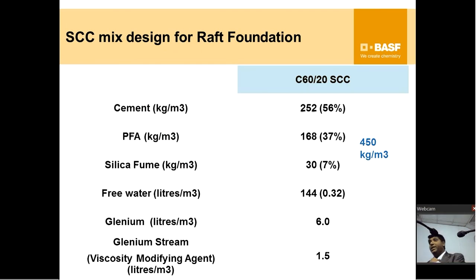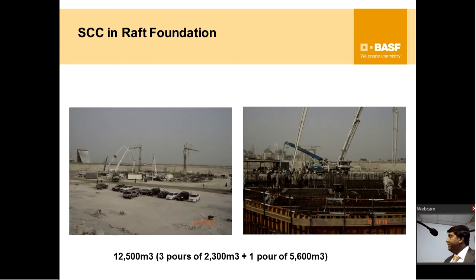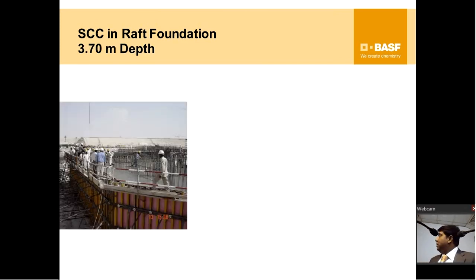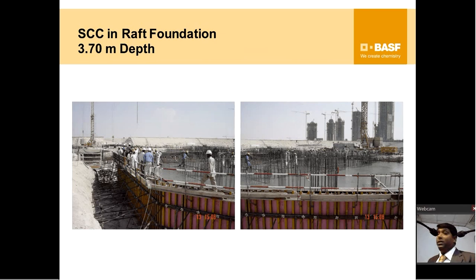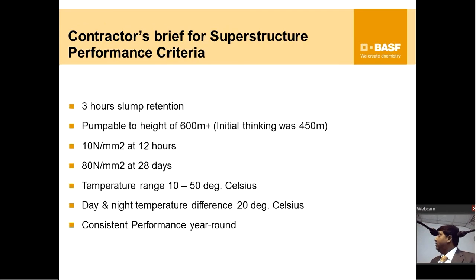A typical mix design for this: C60 SCC for the raft, which means 60 MPa cylinder strength. Cement 252, fly ash, silica fume, free water. Here we used viscosity modifying agent separately. That was the mix design. What they did was split the raft into blocks: three pours of 2,300 cubic meters and one pour of 5,600 cubic meters in one go. SCC was used in the raft foundation, here at 3.7 meters depth, which is the thickness of the raft. So this is how it looks when it is finished.